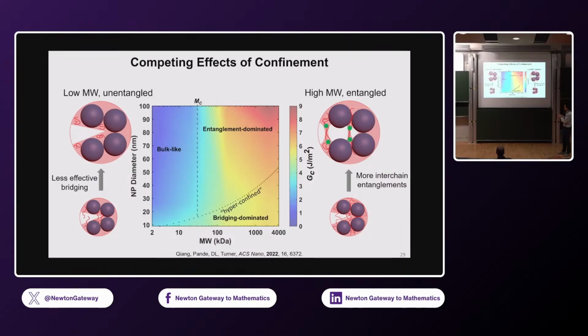However, if the particles are fairly large, that means the confinement ratio is not very high. Okay, so the polymers don't really have to stretch very much. In such a case, within these interstitial pores, you can still retain some of the entanglements. Okay, so it's these entanglements remaining within the pores that lead to toughening. So for larger particles, it's the entanglements within the pores that lead to toughening, whereas for smaller particles, it's the stretched polymer chains that are able to bridge multiple particles that lead to toughening of these materials. And that's the picture we have.